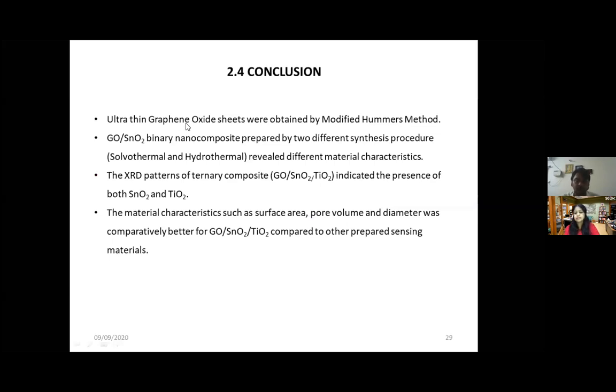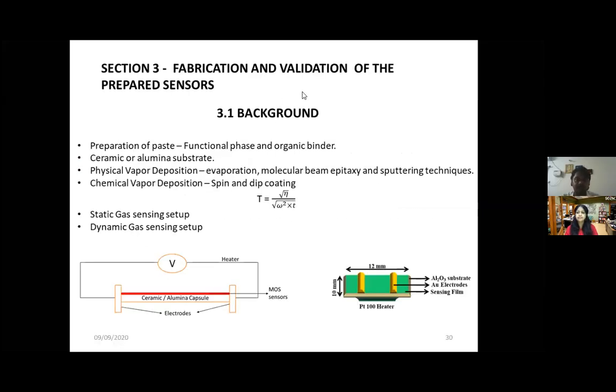So graphene oxide by the modified Hummers method, GO/SnO2 by 2 different methods, 1 part, 2 part. XRD and FTIR tell us that from the original precursor, the metal oxide has been formed. The surface structure properties, which have high maximum gas adsorbability, surface area, and pore diameter for the adsorption of gas, in the sensing material implies that it can be used for fabrication and validation. And next we'll discuss fabrication here.